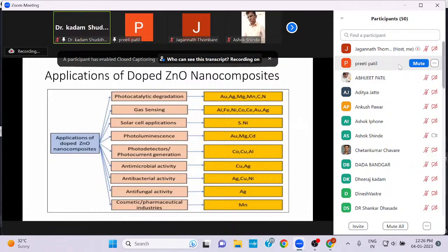Solar cell applications: if you just see nickel as well as tin, they are very successful in enhancing the power efficiency of the solar cells. In case of tin, it is found that 0.05% doped tin almost produces an efficiency of 17.81%.